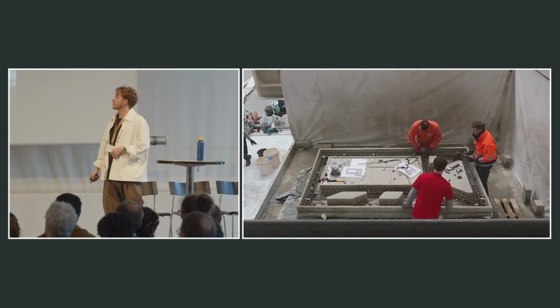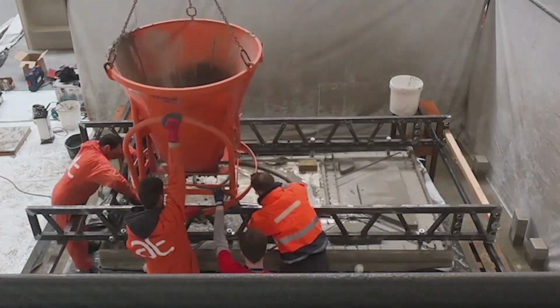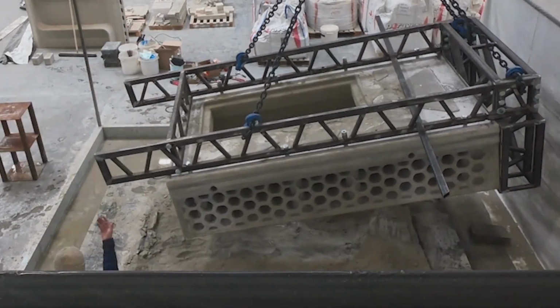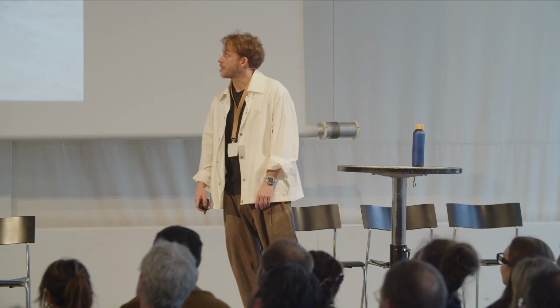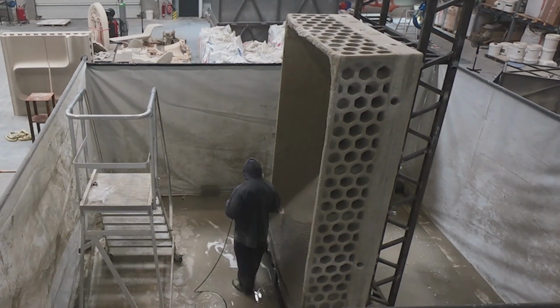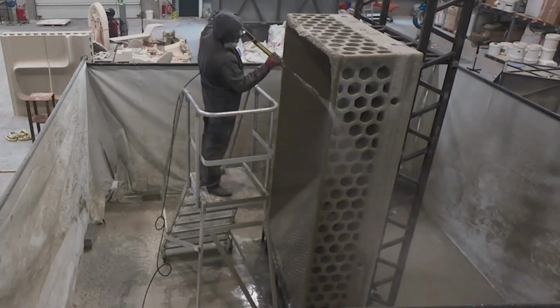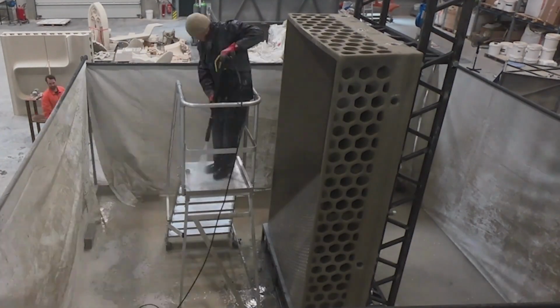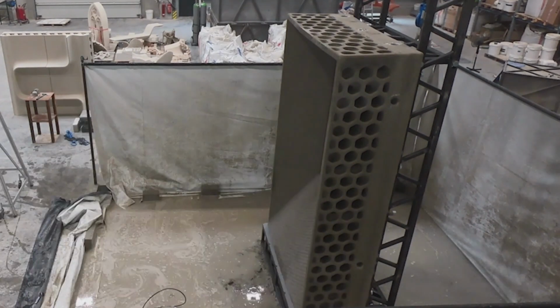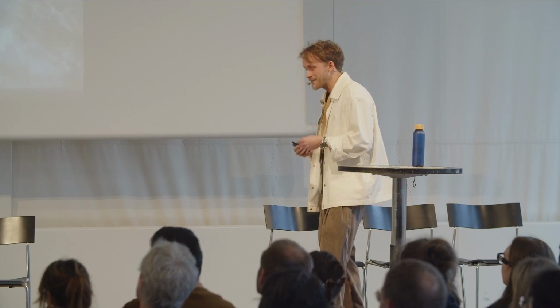Then the rebar is put in, and grouted mortar is filled. And after 1 day, you can start to lift the part by itself. Then the part needs to be turned, and the front side is still not fully hydrated, so this is a game against time. If it wouldn't get hydrated, it would also crack. So it's a delicate play of when to put water where.